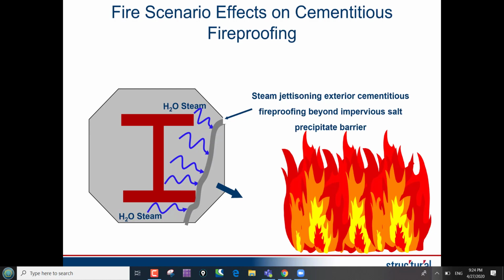the concrete. And we have anecdotal evidence from fires where we can actually see those surfaces are white with crystalline salt products. It's also known as efflorescence and a bunch of other things, but a lot of it is calcium carbonate, and you see that just by anecdotal evidence. That's why it's so important when it comes time to do repairs on cementitious fireproofing. You have to go all the way around 360 degrees circumference of the member. You can't just patch because of the amount of salts in the pores.